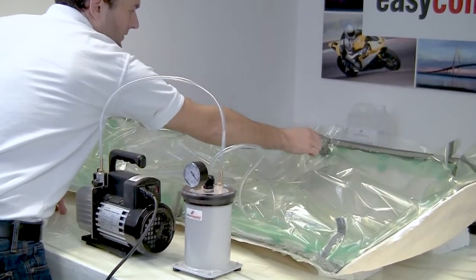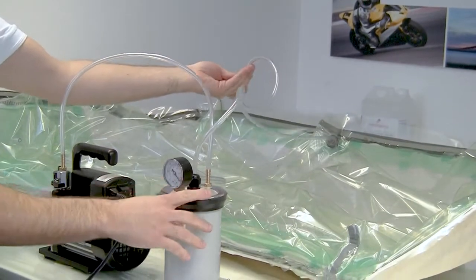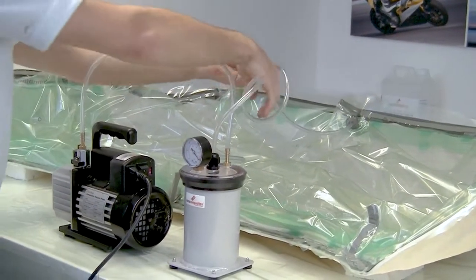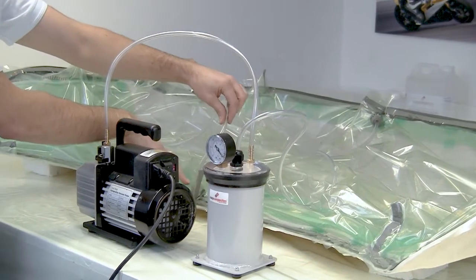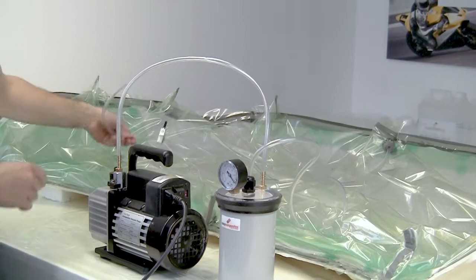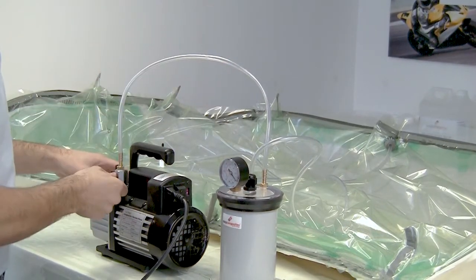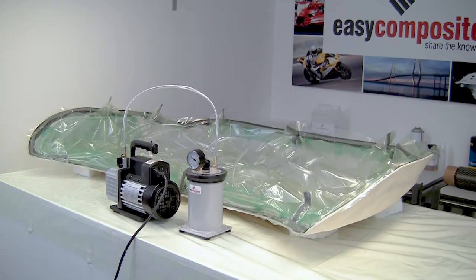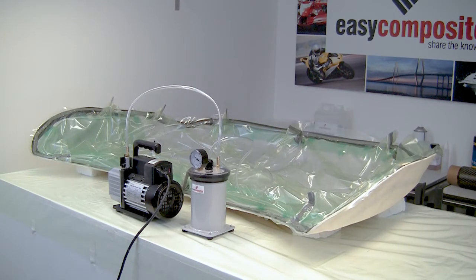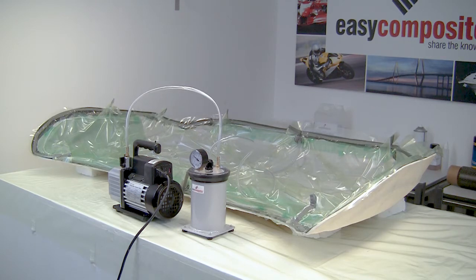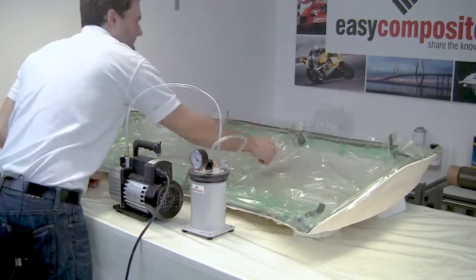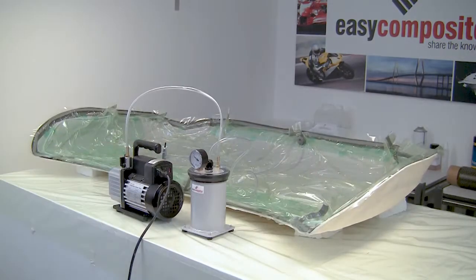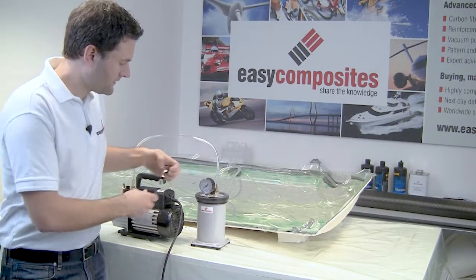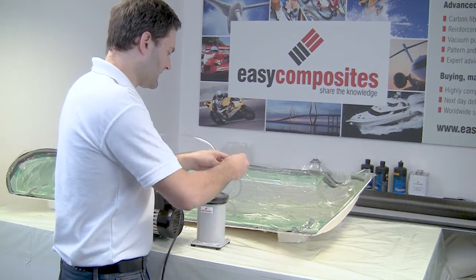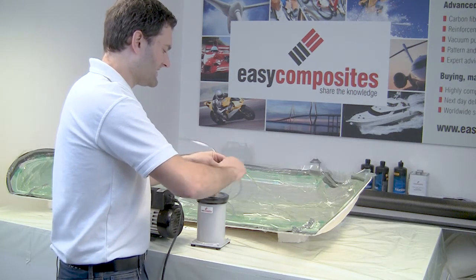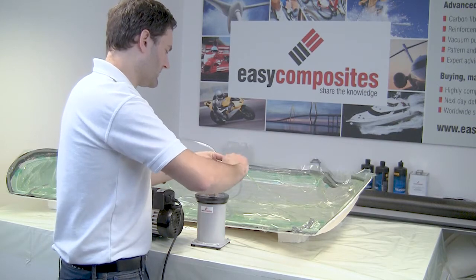At the top of the bonnet here, we've got the vacuum line connected to the catch pot, and the catch pot connected to the composites vacuum pump. And then where we've got the resin feed line at the back of the bonnet, this is just clamped off. So what we're going to do is switch the vacuum pump on and pull a vacuum on this. Finally, before we can infuse, we're just going to clamp off this bag and do a vacuum drop test, which is absolutely essential before we can do the infusion.